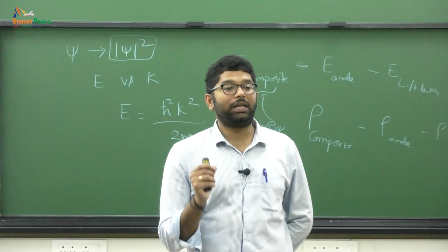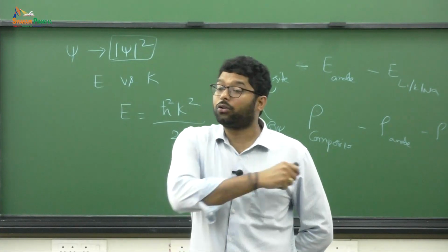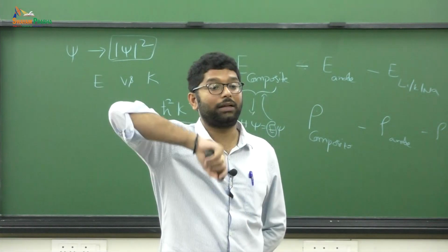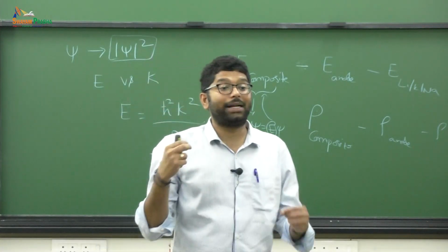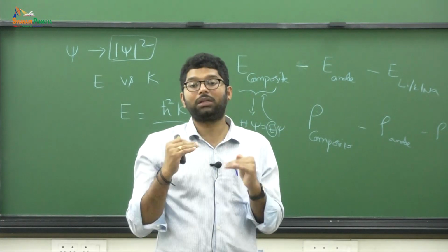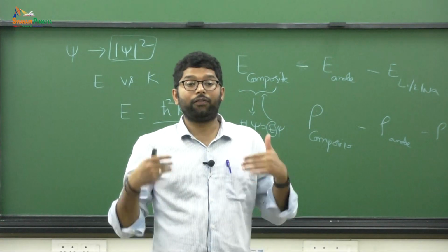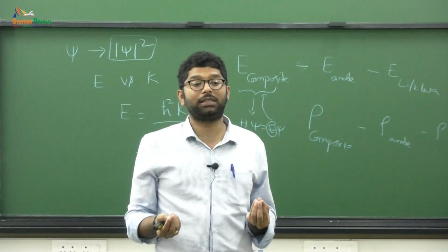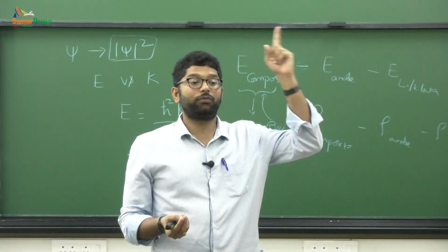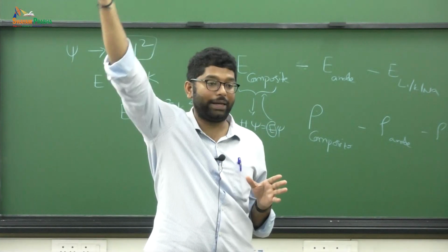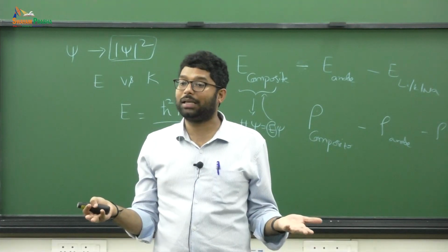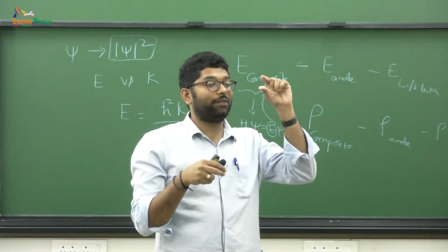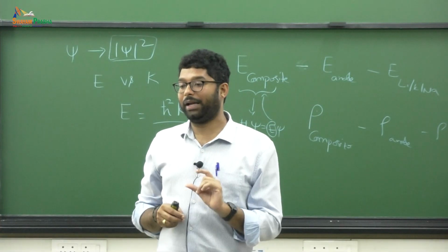So essentially what it is telling you, when you are calculating the migration energy barriers, what will be the one that will be affecting? It is the adsorption energy differences, not the simple adsorption energy. If we were thinking about simply the adsorption energy, then what would you have thought? Potassium would be the one having the highest barrier. But when you see the adsorption energy differences, you can immediately see that it is the potassium that will be having the least energy barrier, okay.